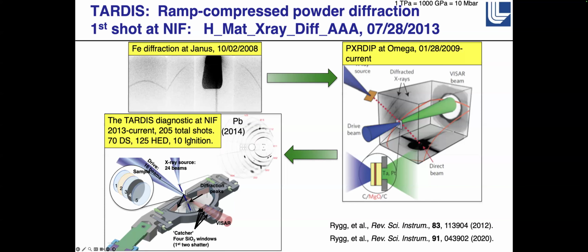In 2013, we transferred to NIF with a target diffraction in situ diagnostic, which we call the TARDIS, which has had a lot of NIF shots, 205 NIF shots, which is quite a bit considering that NIF does between 250 and 350 shots per year. So over 12 years, we've had a lot of shots.